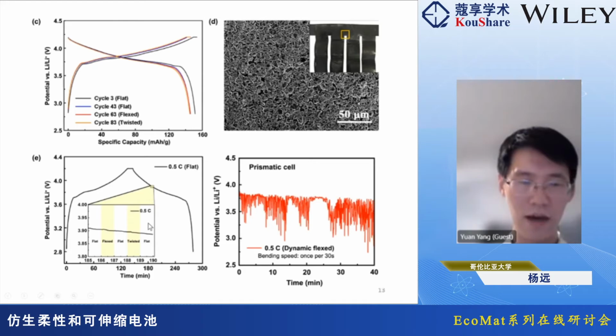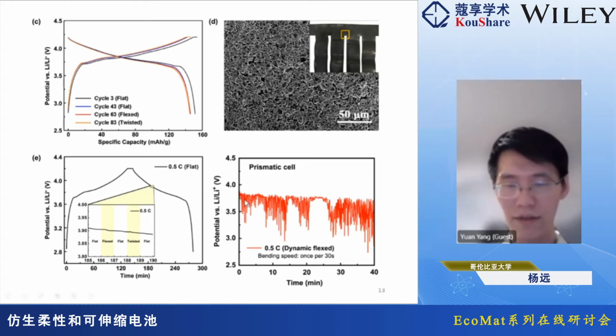So we also run this cell, charging and discharging it while the cell is under dynamic bending for many cycles. You can see that the voltage is very steady, with a change of less than 10 millivolts. On the other side, if you make a prismatic cell with a similar size, bending down to, I think, a radius of 3 centimeters, the same as the left one, the voltage will fluctuate a lot. So this is not acceptable for wearable devices.